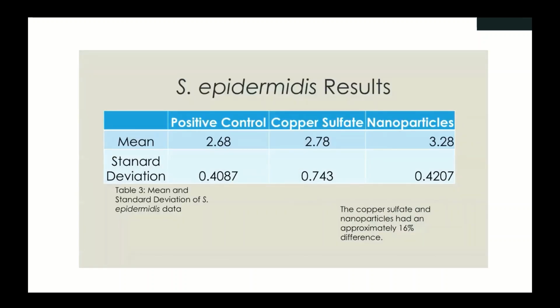We also looked at S. epidermidis, which we looked at earlier with the honey, and the copper sulfate did work, but the nanoparticles worked slightly better, but there was no significant difference. We want to do a further study looking at perhaps pH, temperature, and stir time for the nanoparticle formation to see if the copper sulfate nanoparticles can be enhanced using this plant extract.